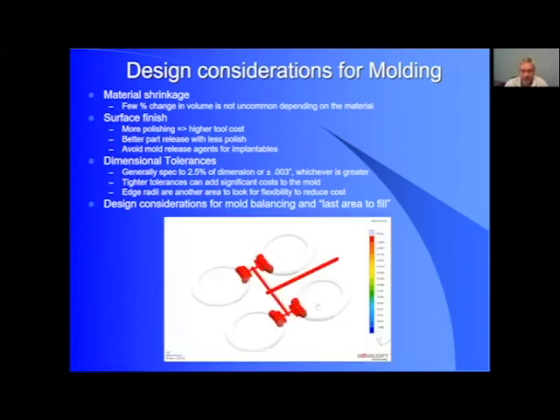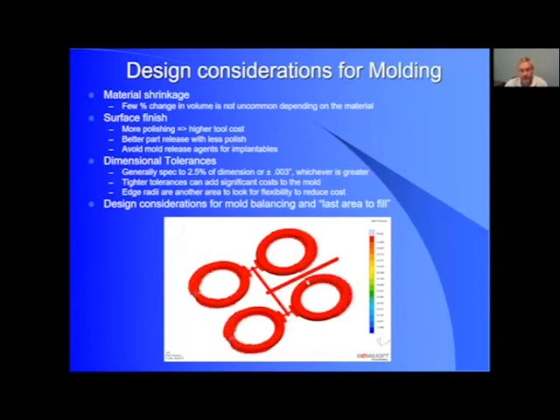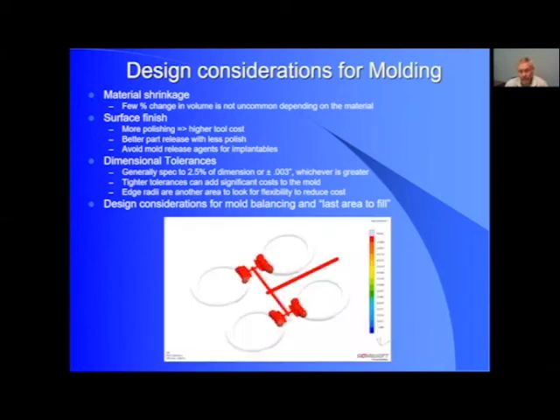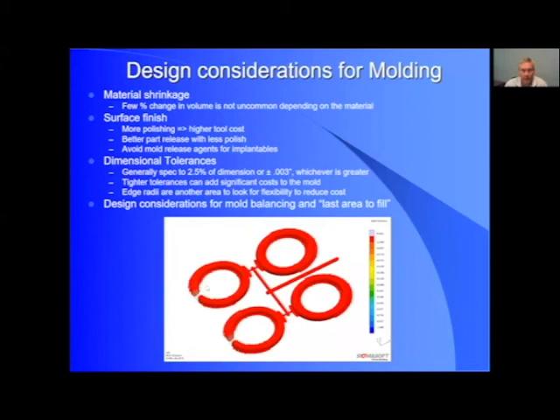You can see that, I'll run it one more time, that the filling of all four cavities is pretty close. These two fill slightly faster than these last two, so that would be, again, a case of something where we'd be concerned about, we'd want to tweak that perhaps a little bit to get even better complete filling, so there's no more pressure buildup in one set of them than the others. You can also see then we've also engineered this tear flash feature, so this little ridge of material here that can be plucked off at the end and making it easy to prepare the finished device.